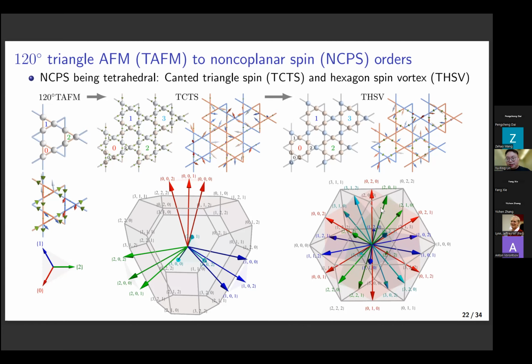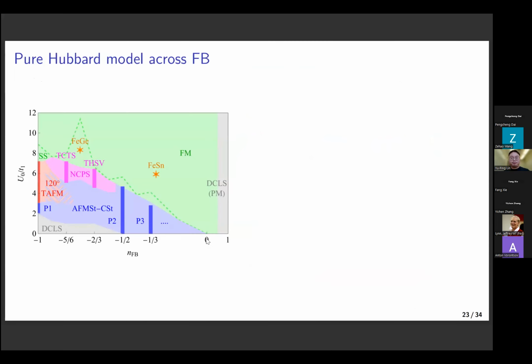And this order is actually related to the previously mentioned Hubbard order, because if we look at the lower density magnetic orders, the lower density lattices are actually forming a kagome structure, and the magnetic order will be corners of the polyhedron, and that will actually be the Hubbard order in the previous discussion. So one key message is that as we increase the filling from the coplanar 120-degree order, the filling not only increases the periodicity, but it also breaks the coplanarity and brings the magnetic order into the non-coplanar spin orders.